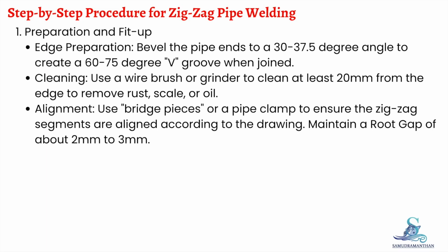Alignment: use bridge pieces or a pipe clamp to ensure the zigzag segments are aligned according to the drawing. Maintain a root gap of about 2 mm to 3 mm.